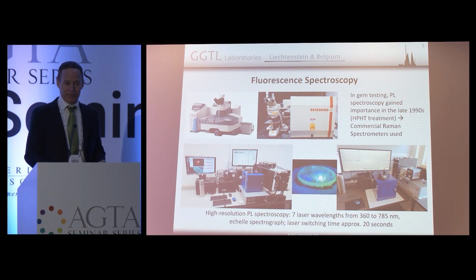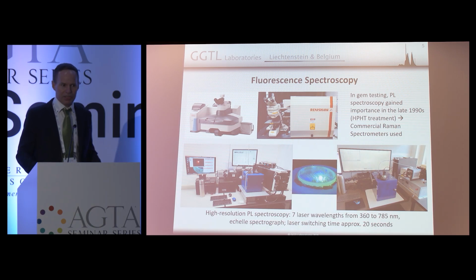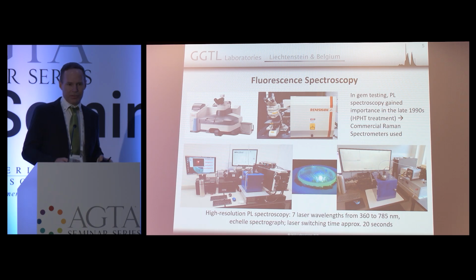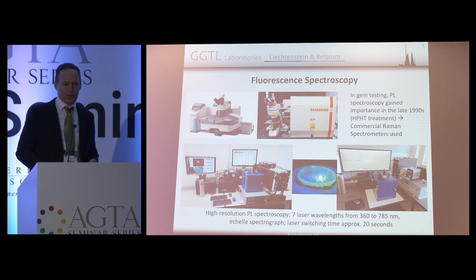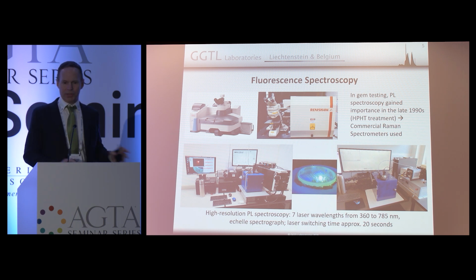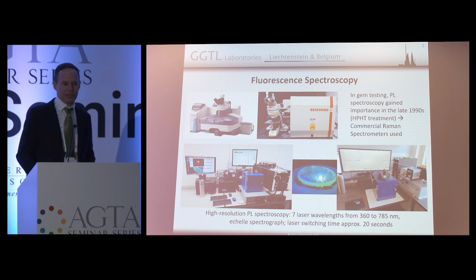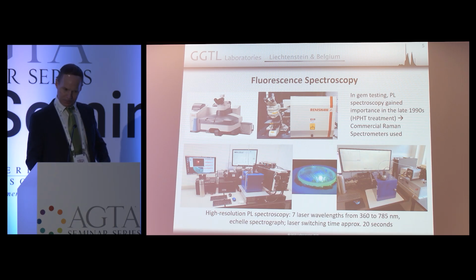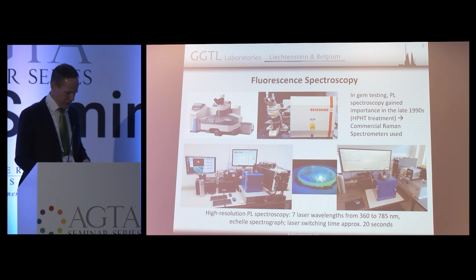So we're currently using 7 laser excitations from the UV to the near infrared. The importance of all these excitations, which I'll show a little later on, along with the imaging, is that the various defects in diamonds that fluoresce do not always show up with the same laser. So you can't just use one laser and think you're going to see everything, but you have to have a big range of lasers available, and you have surprises every time on every diamond. It forces you to use a range of excitations.